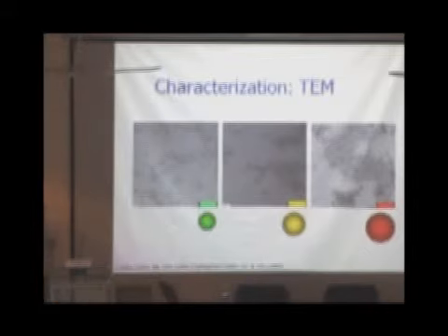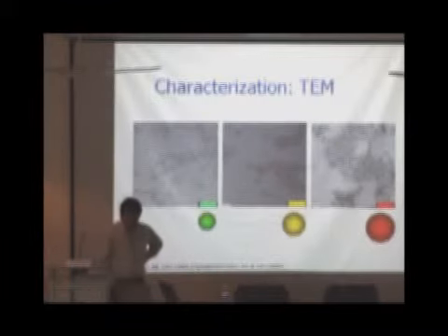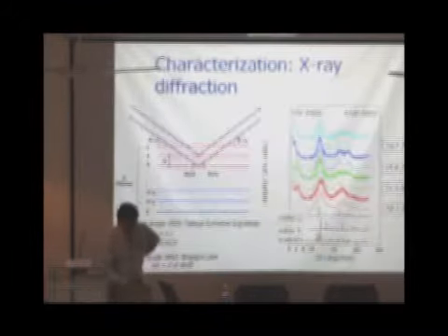And I was telling you about the size distribution. Now I forget the values, but I think these particles are about 2.5 nanometers roughly in diameter, these are about 2.8, and that's about 4.2. But don't quote me on the numbers. You can see that these are very monodispersed in size, and all of them are very crystalline.